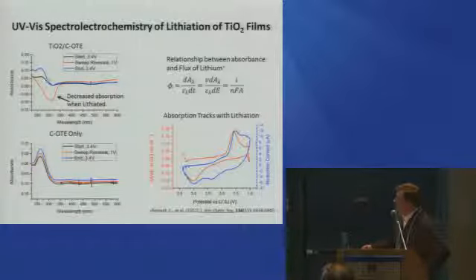Of course, you can plot the derivative of that absorbance with respect to voltage and superimpose that on the current, and you can actually see that this main peak here is where the lithiation is occurring, where the electron's being transferred. And there's all this other surface chemistry that doesn't show up in the spectroscopic signature that is reporting on the charge. Something is being transferred across that interface that shows up as coulombic charge.